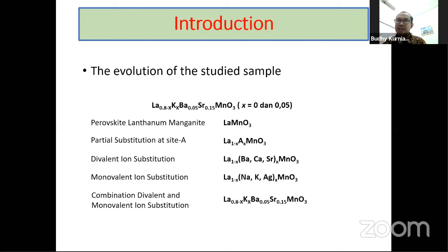For the divalent ion substitution, we see that lanthanum is doped by barium, calcium, or strontium. For the monovalent ion substitution, lanthanum is doped by sodium, potassium, and silver. And also we can mix divalent and monovalent ion substitution. Next, please.